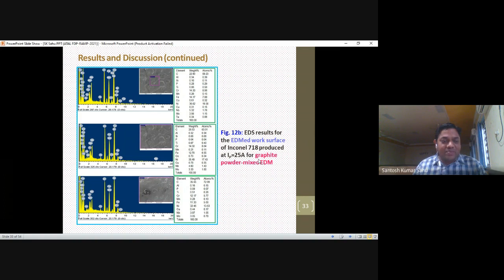And this might be due to the lesser extent of dielectric cracking during the spark discharge, as the addition of conductive powders reduces the dielectric strength of the working medium, and thus stimulates the early discharge to take place. And moreover, the discharge energy was uniformly distributed in the discharge zone, which resulted in heat dissipation in a more favorable manner from the discharge zone during the pulse off times.